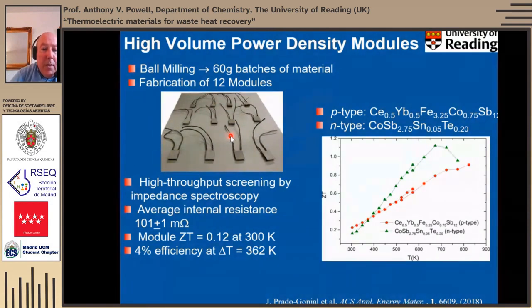They also developed a high throughput screening technique to check these modules rapidly, because module construction is a major technological challenge in its own right. And they found that across the batch of 12 modules, the internal resistance was about 101 milliohms, but only varied by plus or minus 1 across the batches.